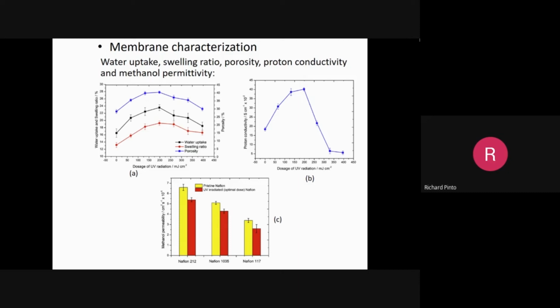Proton conductivity versus dosage of UV radiation, you see here. We found there is an optimum dose of cross-linking. Enhanced cross-linking takes place, but when the cross-linking increases beyond a certain level, the conductivity drops drastically. We did this for Nafion 212, 1035, and 117, that is 50 micron, 90 micron, and 183 micron. In all of them we found a reduction in the methanol permeability, but more importantly, we found an increase in the proton conductivity by more than a factor of 2. See here, and then it drops.